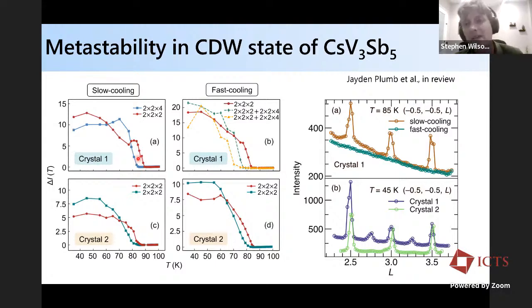But the oddity is that we can then take another crystal, and if we take a razor blade and we just cut it to make it smaller, to make it something that's more X-ray sized, then what we can see is that in that crystal, actually, the 2 by 2 by 4 peaks totally vanish, okay? And so this implies that you have some subtle coupling to mechanical deformation or mechanical strain, and we actually do see a subtle degradation of the crystallinity of the sample once we use a razor blade to cut this crystal. So it's just to demonstrate that the charge density wave state, basically the C-axis modulation in the cesium-based version, is very sensitive to external perturbations.